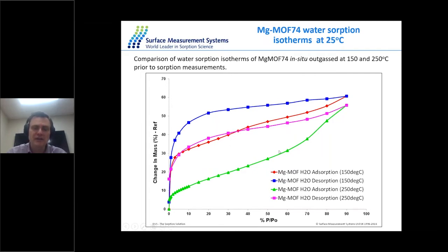So for the material outgassed at 250 degrees, this suggests the structure was destroyed because hysteresis is huge, and the adsorption capacity, if you look at below, let's say, 40%, is quite low compared to 150 degrees. Whereas the material outgassed at 150 degrees clearly shows much higher adsorption capacities and much smaller hysteresis.